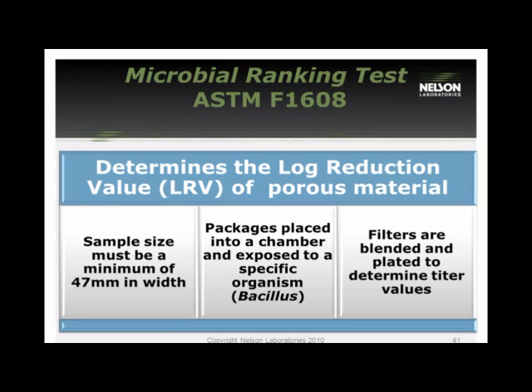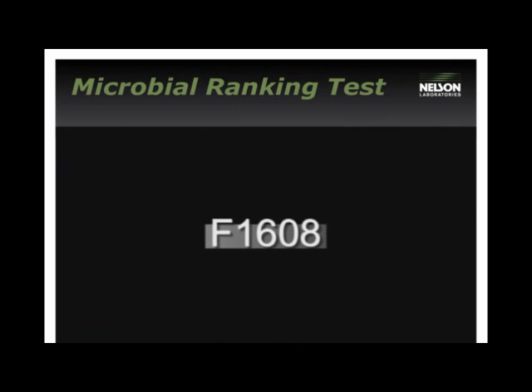It works by exposing the material to organisms, and then we evaluate the filtration of the organisms through the material. The material size is critical. We need to be able to test a minimum of 47 millimeters, and after exposing it to the organisms, we blend up these filters and determine the titer values. They usually are produced as log reduction values, so they're actual numbers.